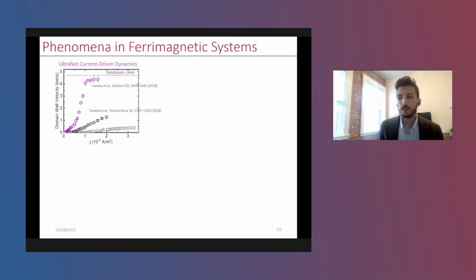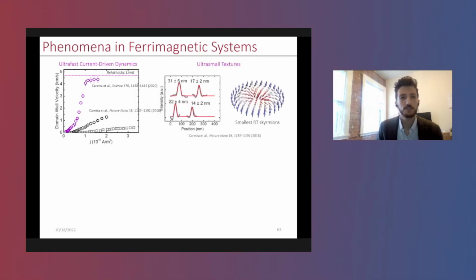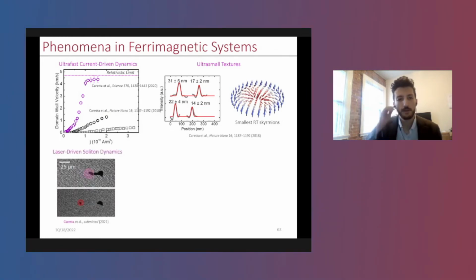I'll just briefly mention before I move on that it's these same compensated magnetic systems that have given us fast domain wall dynamics, but also give us very small spin textures. So we've stabilized some of the world's smallest room temperature skyrmions in these material systems, as small as 10 nanometers in diameter. We can even drive dynamics in these systems, not by using currents or fields, but just by using light. So this work is still ongoing.